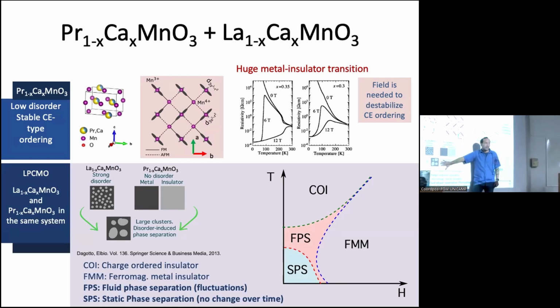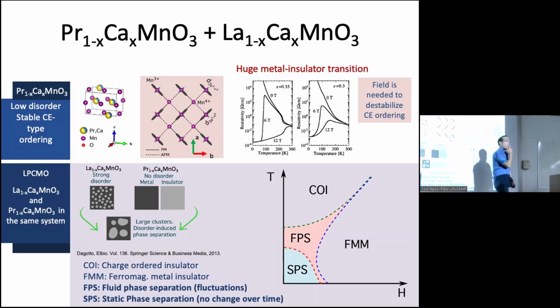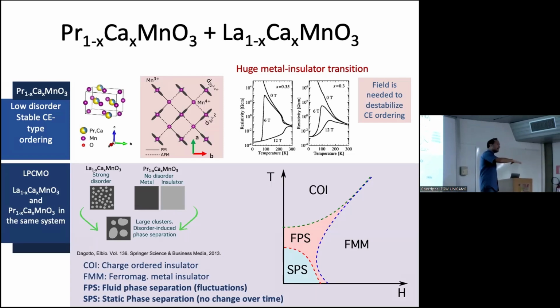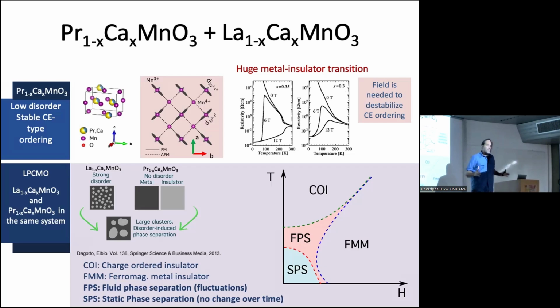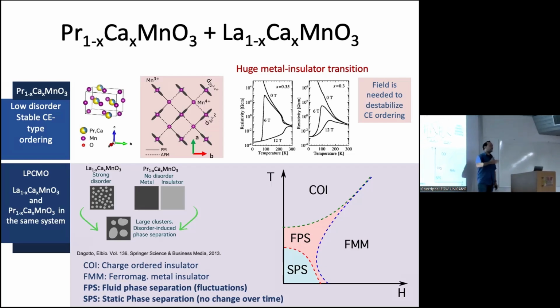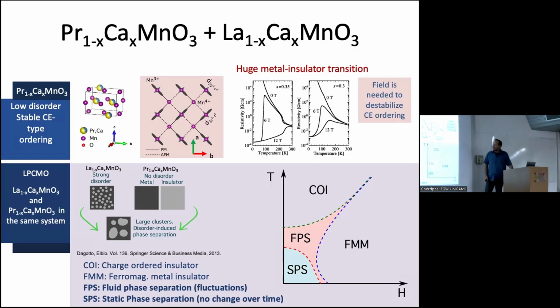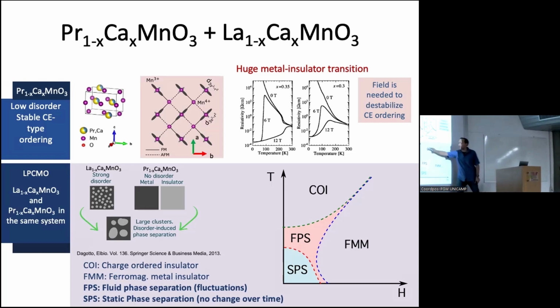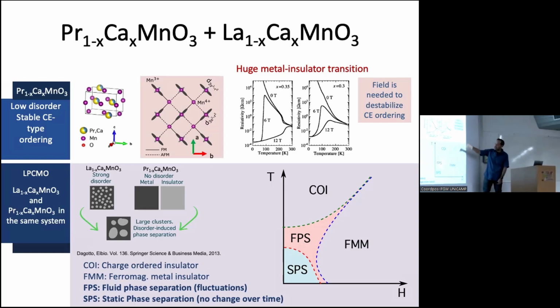So we get the metal insulator transition that we saw with the needed field, and then we have the phase coexistence of the metal insulator, the metallic phases and the insulated. So somehow mixing these two, it gets rid of the necessity of applying an external magnetic field of 6 Teslas. Okay, and that's the beauty of this. So this is the phase diagram, and the message here is that we were able to measure everything here. Okay, all these transitions. And we measure the dynamics.